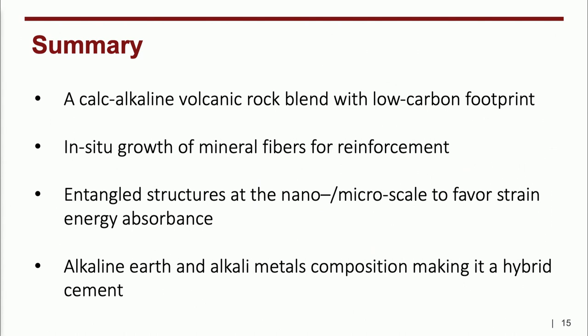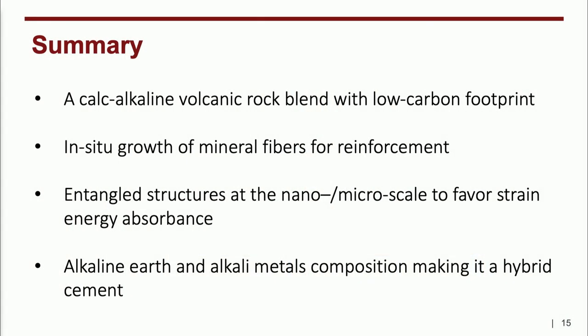So as a summary, we are using a calc-alkaline volcanic rock blend that has a low carbon footprint. We use in situ growth of mineral fibers for reinforcement. And most importantly, the fibers must have an entangled structure at the nano-micro scale to favor strain energy absorbance. And so at the end, this alkaline and calcium composition makes the blend a hybrid that is in between Portland cement and geopolymers.